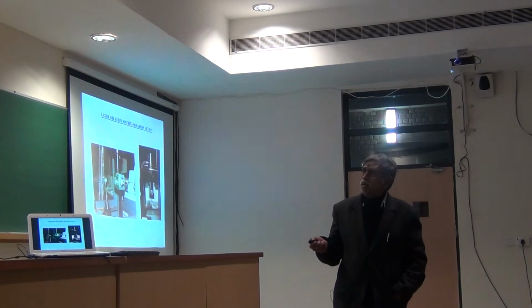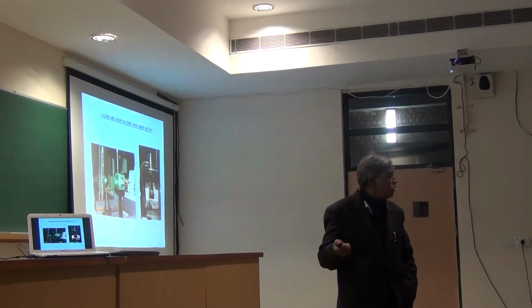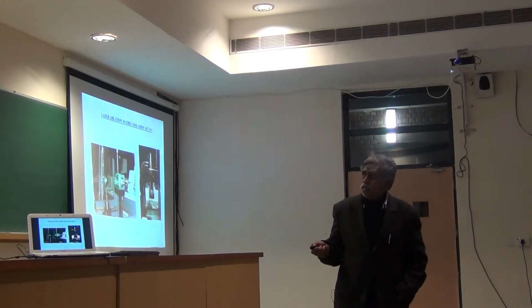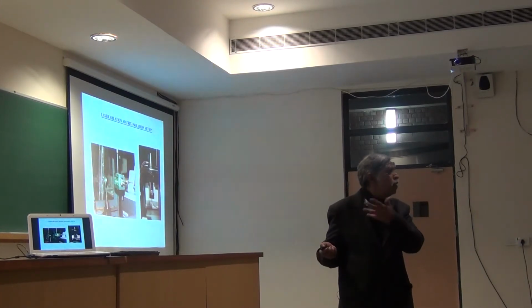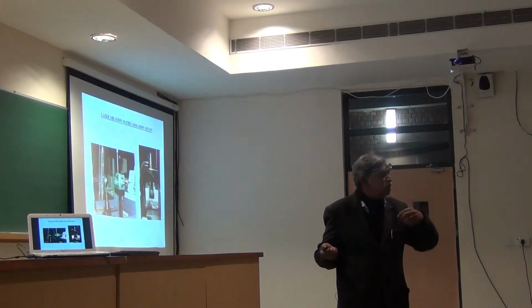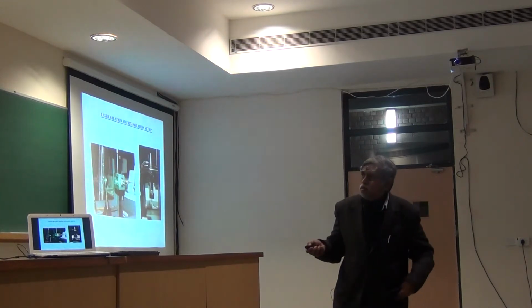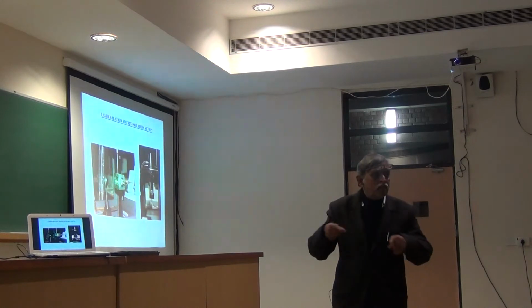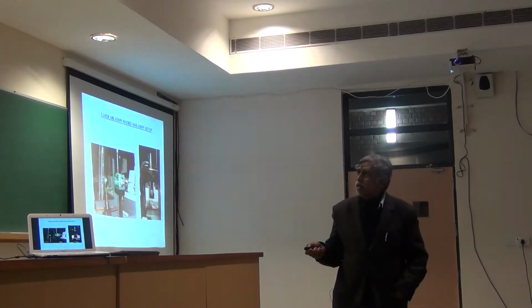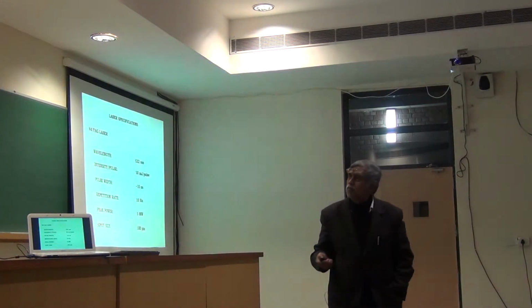The same setup that I showed you earlier, you can see a little green out here. And that green is essentially because we were shining a second harmonic of a YAG laser, 532 nanometers, which is green. And that is basically what we focused inside to do the laser ablation. This is the cryostat. The material is inside here. The substance that we want to ablate is kept inside. The laser hits it, produces the vapors, and of course through this line we send argon, and the two mix and form your thin film. And once it is done, it is pushed into the spectrometer for recording your data.